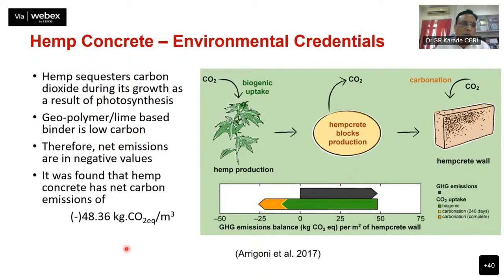And when we talk about the carbon emission, in this picture you can see how this carbon emission is calculated. During its growth itself, it absorbs a lot of carbon dioxide in photosynthesis. However, in transportation and manufacturing, there is some carbon emitted. And while in use, if we use lime-based or geopolymer-based binders, it absorbs carbon dioxide again. So the net carbon emission is negative. It's minus 48.36 kg per cubic meter of hemp concrete. That's the main feature of this concrete.